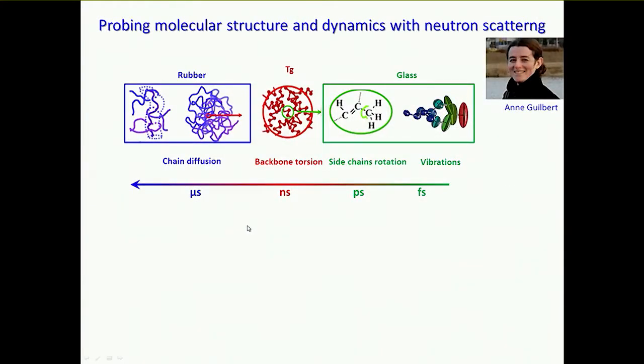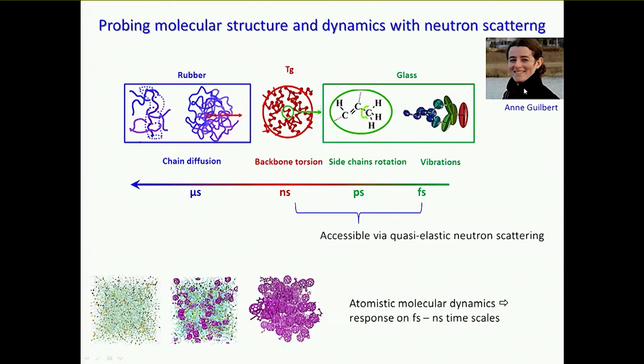This is work that we were addressing using a technique of quasi-elastic neutron scattering, which is not so easily accessible, but once you have access to it, you can learn quite a lot. Quasi-elastic neutron scattering gives us access to the dynamics of side chains and backbones on a time scale somewhere between nanoseconds and femtoseconds. So you get data out, but we were also able, and this was the work of Anne Guilbert in my group, to make at the same time an atomistic molecular dynamics study of the different systems that we looked at.